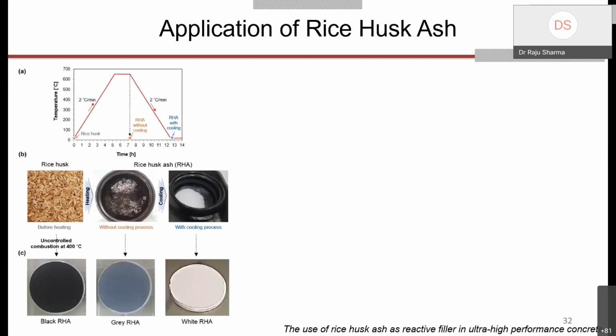Now there is one example of how the RHA property changes with the different processes. First, in the top left image, you can see the temperature profile: the temperature increases at 2 degrees Celsius per minute, and in approximately 5 hours the maximum temperature of 600 degrees Celsius is reached. Then it is burned for 2 hours at 600 degrees Celsius, and then cooled at 2 degrees Celsius per minute. It takes a total 13-hour journey for the rice husk to become the material.